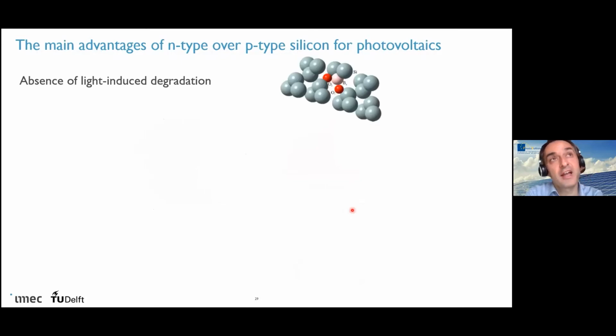So as I mentioned, people are considering switching more and more to N-type wafers. Why is that? Because N-type wafers have a few advantages if you go to high efficiency devices over P-type. First, there's the absence of light-induced degradation. I mentioned it before - if you have boron in your wafer, you can have boron-oxygen complexes, and this can lead to degradation. Now this can also be solved by going to gallium-doped P-type wafers, so we don't really only need N-type to solve this.